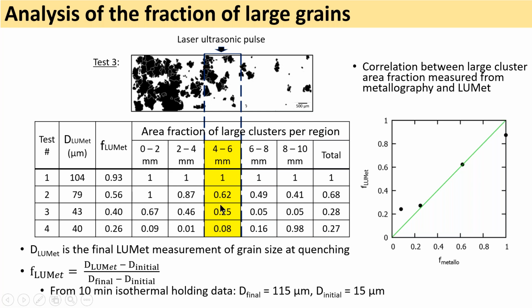And what we have tried to do is correlate the fraction of large grain size measured by LUMet and the fraction of large grains by metallography. What you can see here is that you actually have a very good correlation between those two in the range of interest. So it tells us that the measurement of grain size using LUMet is an average of the grain size in the zone which is measured by the pulse. And it's also a very good tool to predict whether this particular temperature is susceptible to the presence of abnormal grain growth.